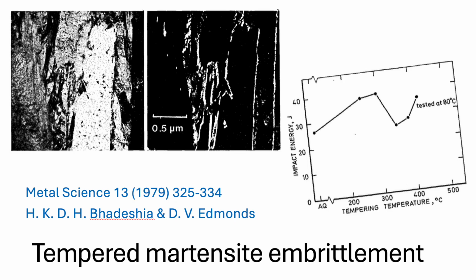Well put. And that fragility, dictated by features so incredibly small they require powerful electron microscopy just to even see them, it really highlights the absolute necessity of extreme precision in engineering these materials. It really does. And maybe the final provocative thought for you to mull over is this. Knowing now that the specific mechanism causing TME varies so critically based on tiny differences in alloy composition and the resulting phases like retained austenite, how much variability in even tiny amounts of RA, say between 2% and 5%, can we truly afford when we're designing critical high-strength steels?